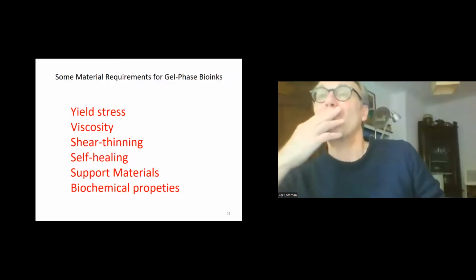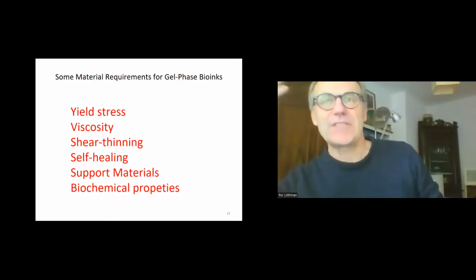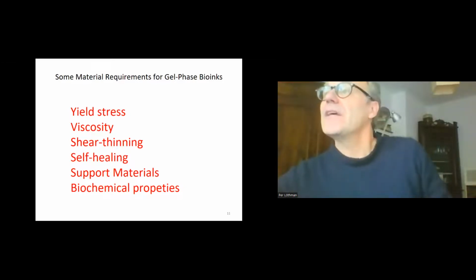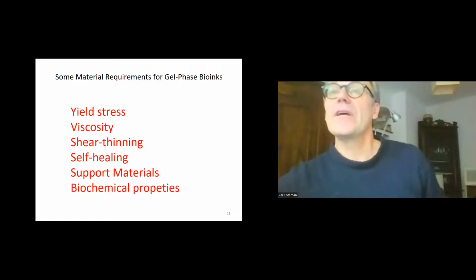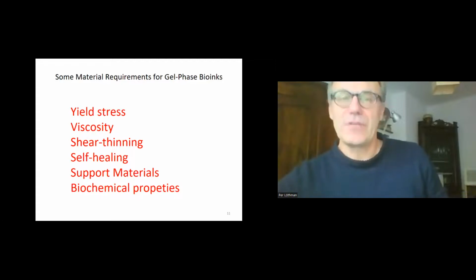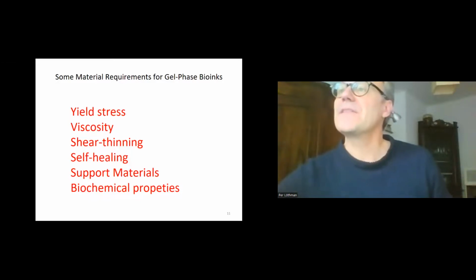Yield stress represents the stress needed for a gel to begin to flow, and we also need a certain viscosity as well as yield stress to prevent cell sedimentation, and we need a sharp decrease in the viscosity in order to make the bioink printable. Now, there's a fine balance. If the yield point is too high, we might need very large pressures, and we cannot always achieve that. And this itself can also lead to cell death, right?